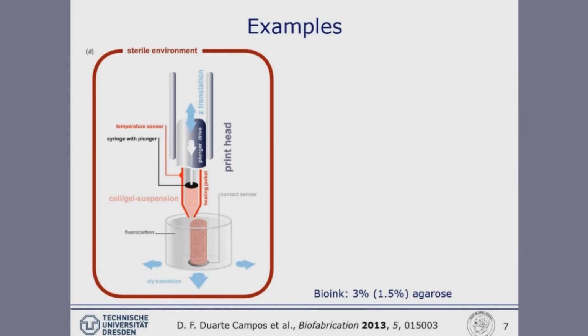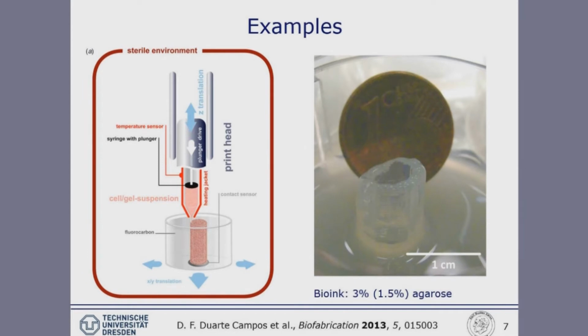One comes from the lab of Horst Fischer here in Aachen, Germany. He has published recently about the utilization of an ultra-hydrophobic fluorocarbon. I'll try to show this with a mouse on the slide. So the printing process is done in a liquid of a completely inert organic solvent, as I've mentioned, an ultra-hydrophobic fluorocarbon. And therefore, this material stabilizes anything you are extruding in this volume. And therefore, for example, geometries like this hollow tube could be fabricated with a size of around 1 centimeter. Behind this is a 1 cent coin.